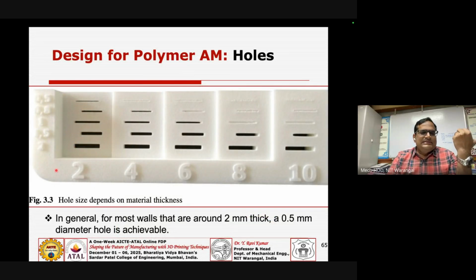And then the thickness is another matter. If it is 2 mm thick, all your 0.5 mm holes or slots can be realized, from 0.5 to 2 mm. But if you increase the thickness of the wall, it may be 4 mm, but this feature is missing, right? So we need to understand these constraints. Then based on that, we need to redesign these holes, or come out with a kind of guideline which should be followed.